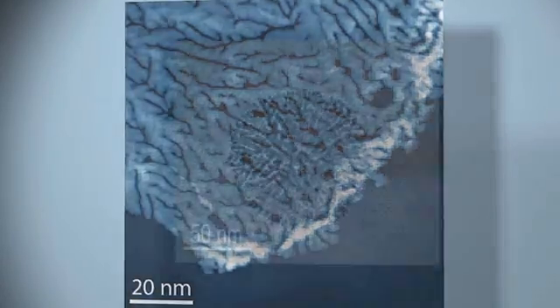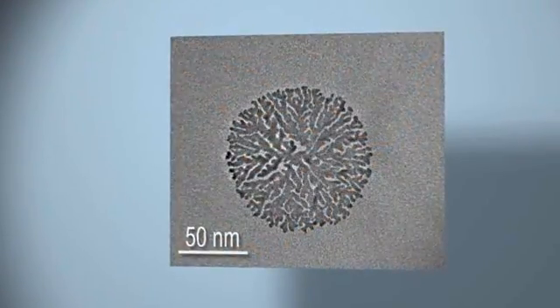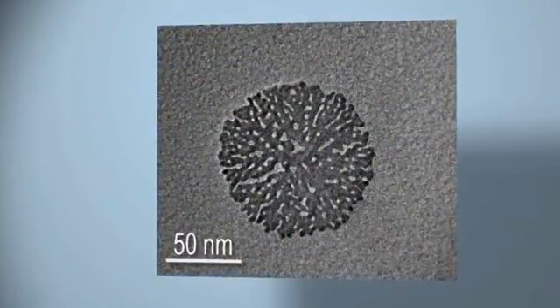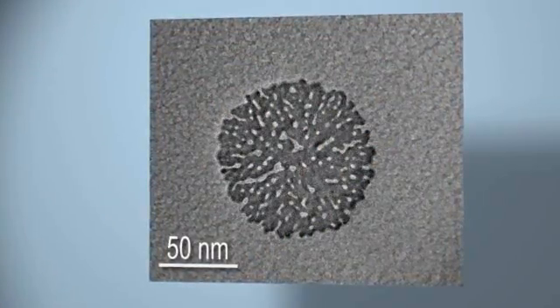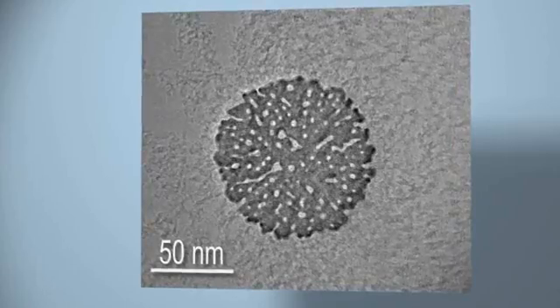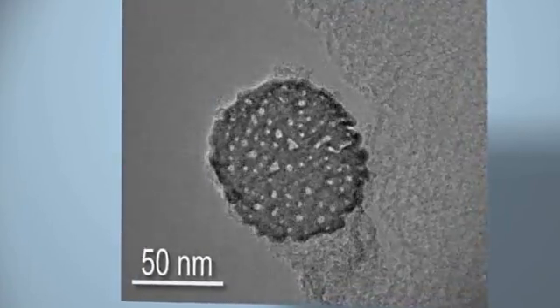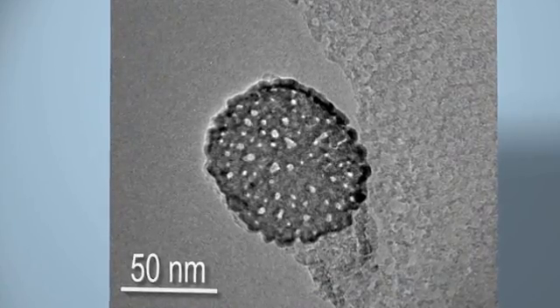And then they have this added feature that when they begin to change during operation in the fuel cell or by heating and other processes, they do what's called ripening. Small structures begin to get larger feature size. But in this case, they form what's called a holey sheet.